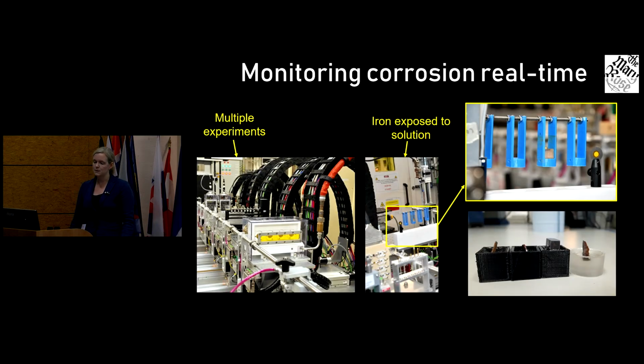And then the last experiment that we've been doing on the iron, this is on I-11 at Diamond. They have a back hutch, which is for long duration experiments, so we've been running this for well over a year. Here you see robotic arms, and there's a whole range of different experiments there, and they have every Monday blocked out that they will put each of those experiments in the beamline and run X-ray diffraction on them. So we set up an experiment where we were looking at marine archaeological iron, Mary Rose iron, some freshly excavated marine archaeological iron, some modern day equivalent iron, and also some synthetic akaganeite.